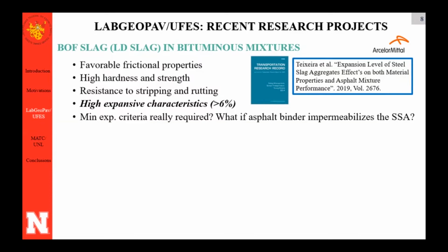This requirement, when it was made, was more thinking about the use of slag in base and sub-base, which is indeed in contact with water and not much with heat, but water, and the material can expand. But in the HMA layer, this material maybe will be surrounded by asphalt binder, and the asphalt binder can protect the slag and avoid this expansion. That was our initial hypothesis. Why we evaluate if this slag will really expand when used as an aggregate for asphalt mixture production.